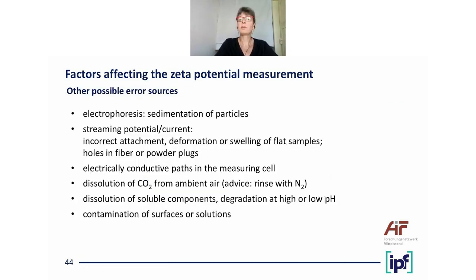There are a lot of other possible error sources. For instance, in electrophoresis, if the particles are too big, if they sediment or agglomerate, then we get wrong values. For streaming potential or current measurements, errors may arise from incorrect attachment of the samples, or a deformation or swelling, or if the fiber or powder plugs are not prepared properly and you have holes, then you also may measure wrong values. Another problem are electrically conductive paths in the measuring cell. If you measure with electrically conductive materials, that's always tricky.